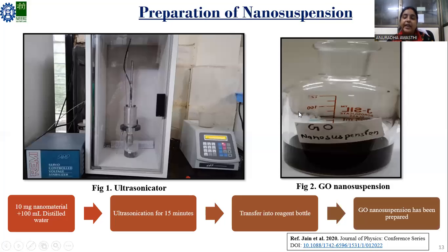So here we have prepared the nano suspension of graphene oxide. As I already told, graphene oxide was prepared as a hydrophilic material. For the nano suspension, we use an ultrasonicator. We take 10 mg of graphene oxide and mix with 100 ml of distilled water, ultrasonicate for 15 minutes, and transfer these in a reagent bottle. It was a sustainable and stable nano suspension.